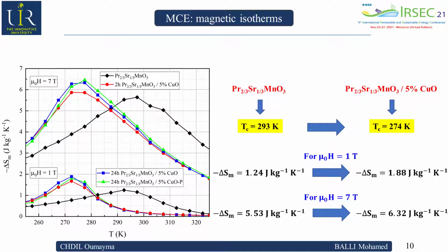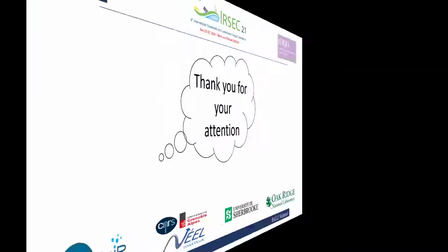A variety of mechanisms may explain this reduction in transition temperature and magnetic entropy. To start, there is a loss of ferromagnetic interaction caused by the inclusion of the copper oxide. Second, the presence of copper oxide altered the double exchange interaction through the remarkable structural deformation. The high grain size of the composite, on the other hand, may promote a more ordered ferromagnetic phase and therefore reduce the width of the magnetic transition.